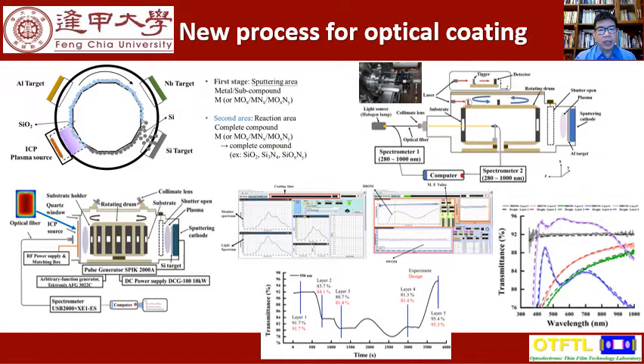In my lab, we have developed a homemade plasma-assisted reactive magnetron sputtering system. The sputtering power could be modulated as DC, pulse DC, HiPIMS, superimposed HiPIMS adding medium frequency, deep oscillation magnetron sputtering, and the plasma-assisted reactive magnetron sputtering process. A home-built ICP system is used as the plasma assist source for compound reaction.